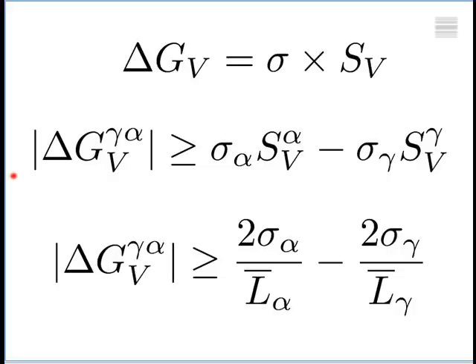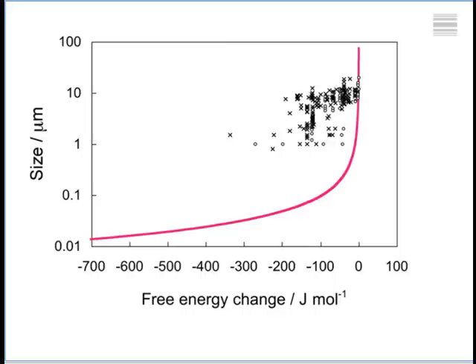And if I plot this as a graph, this is the line I would get, okay? So here is the driving force where austenite and ferrite are in equilibrium. As I go below the equilibrium temperature, the free energy change increases, and I'm able to get finer and finer grain size. And this is the theoretical limit of the grain size you can get. If you want to produce a fine grain size, you have to undercool the steel until you get a large enough free energy change. This is the theoretical grain size.